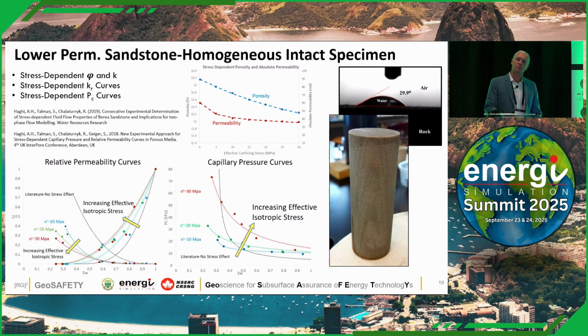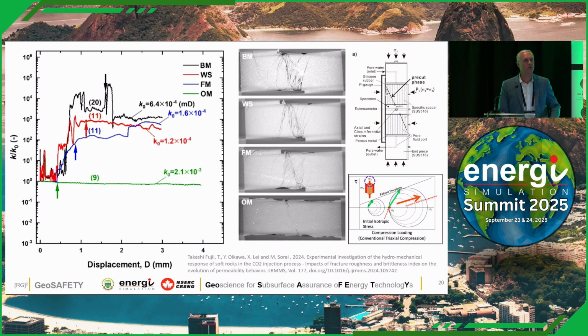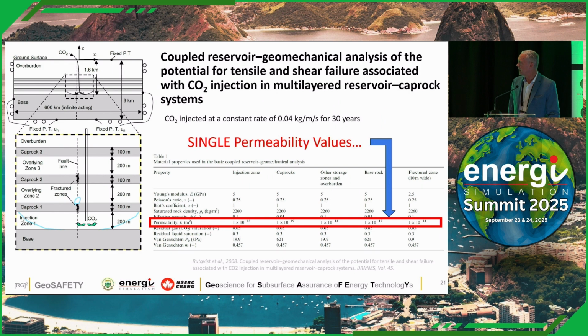Go to tighter material, much more familiar with the sandstones that we're injecting into for CO2 and perhaps for underground hydrogen storage and so on. You can actually have geomechanical impacts that will shift relative permeability curves. You get the standard response normally, but it will shift capillary pressure curves, and it all depends on what stress path you follow. And now if you're under shear, Giovanni showed much bigger pictures. This was some interesting work done with a CO2 project in Japan, and they tested a bunch of different materials and looked at how the shear, but you can look at what happens in this stress path, in this particular case, with the permeability change. Again, all sensitive to stress path.